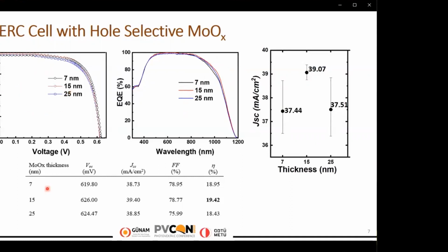And 7 nanometer molybdenum oxide exposes part of the silicon surface to silver, resulting in increased recombination, which leads to low VOC. 25 nanometer molybdenum oxide also imposes extra resistance losses, which causes high contact resistivity and low fill factor, and more parasitic absorption of light due to increased oxygen ion concentration with increasing molybdenum oxide thickness, resulting in modest EQE response and lower JSC.